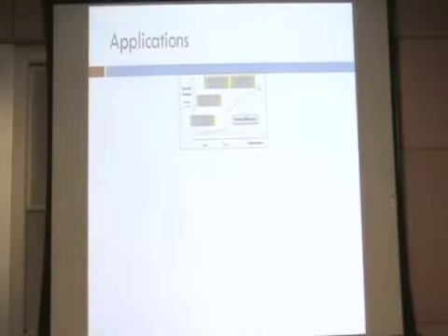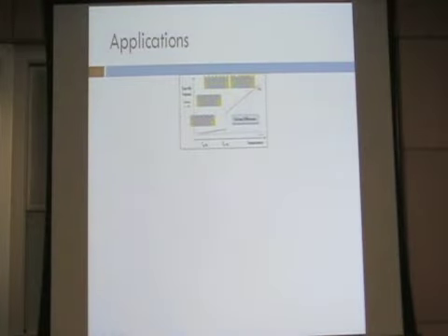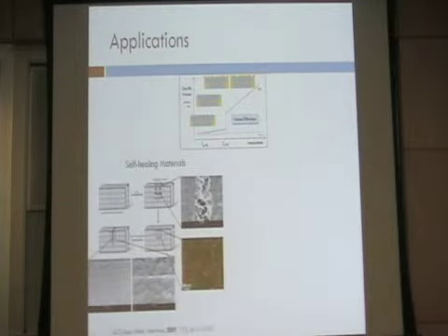So we explored the applications of this bleeding phenomenon. The first thing we did was self-healing of the material. If the material is damaged with a crack, we can trigger this bleeding, and the crack can be filled and essentially rebonded by recrystallization.